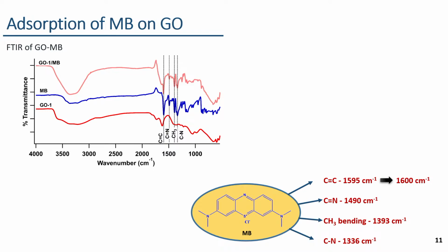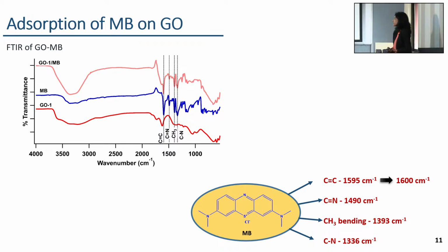Okay. So, here I have shown the FTIR spectra of methylene blue adsorbed graphene oxide along with the FTIR spectrum for methylene blue and bare graphene oxide. In the FTIR spectrum of the methylene blue, we can identify some dominant IR peaks of methylene blue, which I have listed here. In the spectrum of the methylene blue adsorbed graphene oxide, we can see the incorporation of these IR peaks corresponding to the methylene blue, which confirms the adsorption of methylene blue onto the graphene oxide.